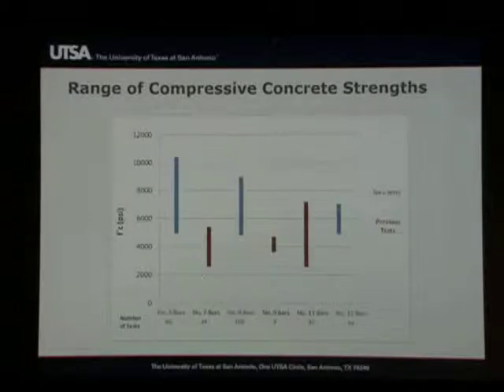In the context of compressive strengths, that's also an important contribution of the study. If you look at the range of the tests that were done before, most compressive strengths were below 6,000 PSI, with a few maybe ranging up to 8,000 PSI. One of the stated goals of this study, and this bar here for number 11 test hasn't been updated, but all of these have gone up to, we have tests ranging up to 15,000 PSI, which are included in the results that I'm going to present. So that was another one of the stated goals, to understand what happens when we use high-strength concrete. Particularly significant in the AASHTO code, because the AASHTO code will allow you to design hooks for compressive strengths up to 15,000 PSI concrete.